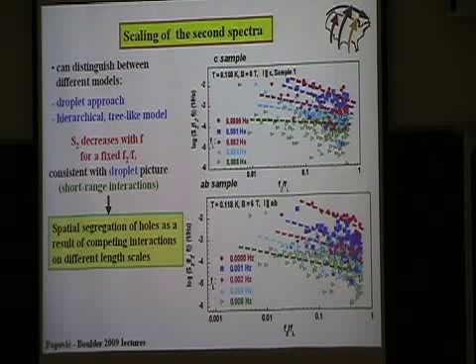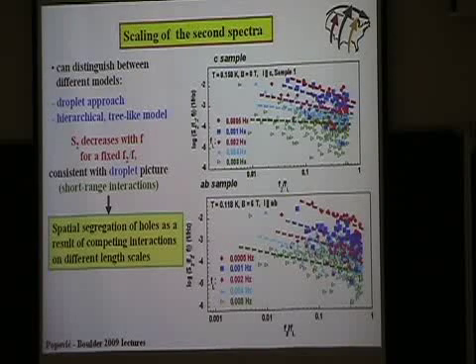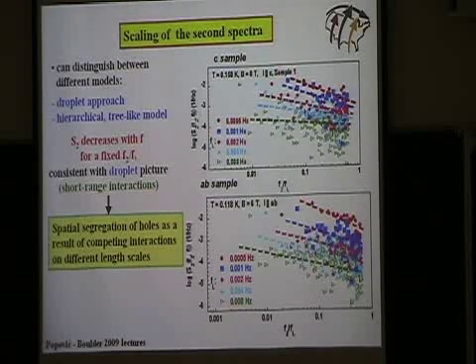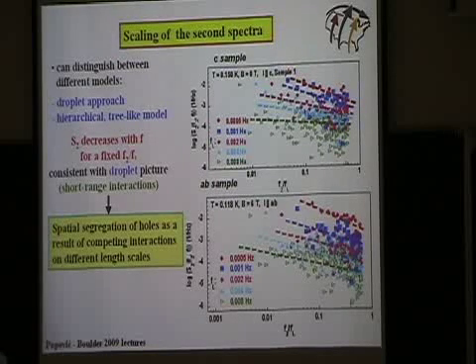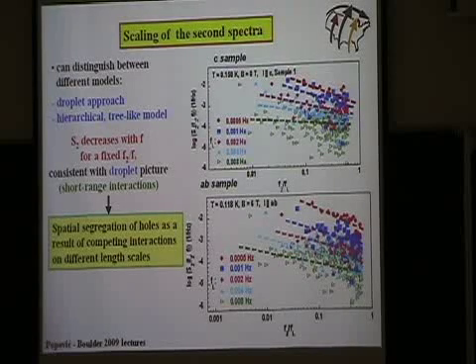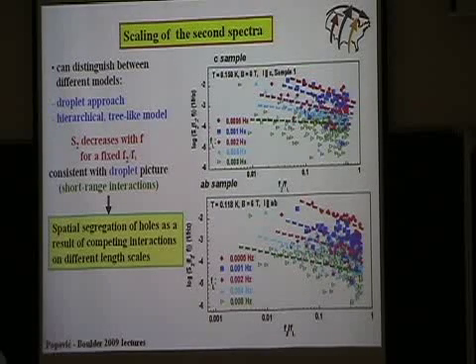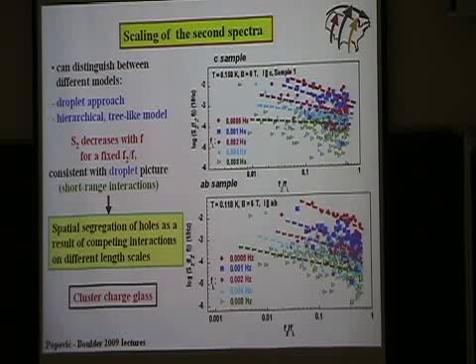the data are consistent with the droplet picture, which assumes the existence of some short-range interactions. And in fact, this is not so strange because people do believe that there is an effective short-range attraction between holes in these materials, and we also know that we do have a Coulomb interaction. So the conclusion is that these holes turn into clusters, they cluster, as a result of the competition between interactions on different length scales. And in fact, there is a theoretical paper, Schmalian and Wolynes, where they show that even in the absence of disorder, when we have a competition between interactions on different length scales, this can give rise to glassy dynamics.